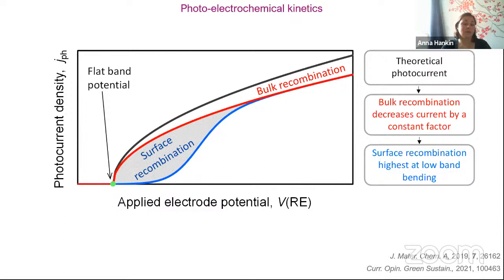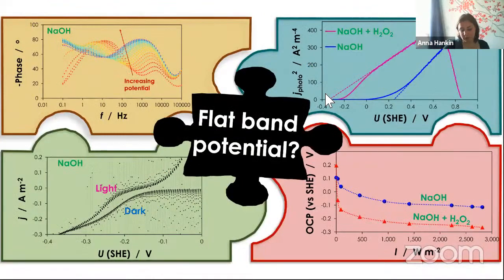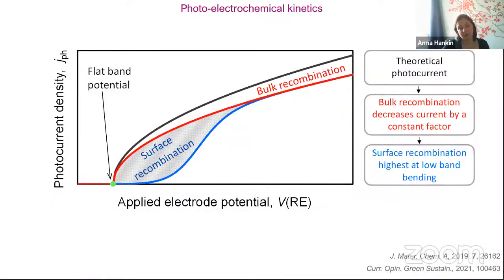But that model neglects fundamental sources of recombination. The first one is bulk recombination, and it decreases the current that you measure by a constant factor. This is recombination of electron-hole pairs before the charge actually crosses the interface between the electrode and the solution. And then you have surface recombination, so losses through the transfer of charge at the very interface. But the point is that all of these effects are relevant to what's called the flat band potential, which is indicated here in the green dot. The flat band potential theoretically is when the bands in the semiconductor are completely flat, meaning that it's a good reference point for when zero photocurrent should flow in a material.